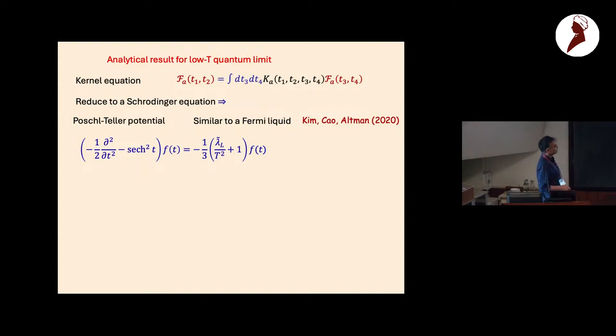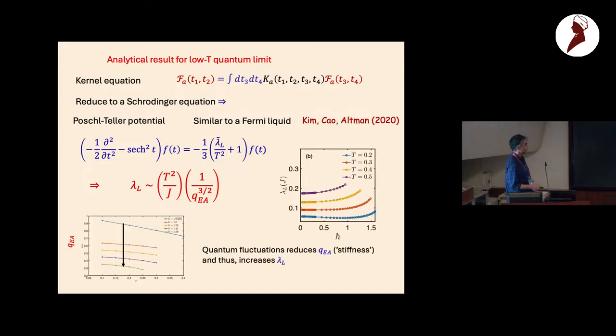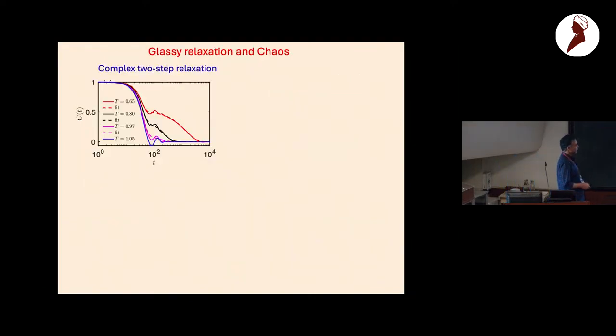Okay, so it turns out in the spin glass phase you can solve these equations exactly under some assumptions. The main point, why the chaos increases as you increase the quantum fluctuation, is that this Lyapunov exponent is inversely related to the Edwards-Anderson order parameter, okay? When you increase h bar, the Edwards-Anderson order parameter goes down, and that's why lambda L increases. It's basically destruction of the order by quantum fluctuations that increases this Lyapunov exponent in the spin glass phase.